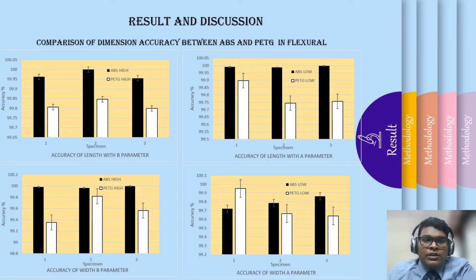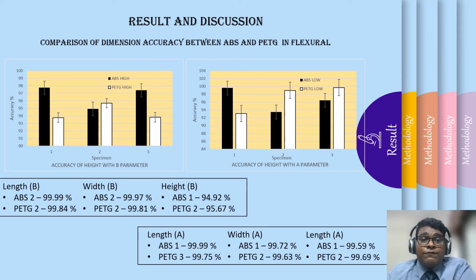Moving on to the dimensional accuracy for flexural, I have plotted a graph according to length, width, and height by comparing the dimensional accuracy of ABS and PETG. From here, we can see that using the high-level parameter, ABS has better accuracy than PETG. The black indicates ABS while white indicates PETG. The same goes for the low-level parameter: ABS has better accuracy than PETG. By comparing the surface roughness and dimensional accuracy, overall ABS has better quality than PETG.